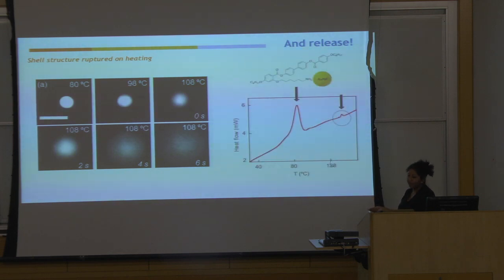And the reason why the shell breaks at those temperatures, we can understand when we look at the behavior of this molecule, the ligand that we put on the gold nanoparticle, the one that is causing the shell formation. It has one transition here around 80-something degrees, another one over here, slightly above, around 130 degrees Celsius. So somehow in between the two, there is a small bump over here, and somewhere here is where the ligands are weakening.